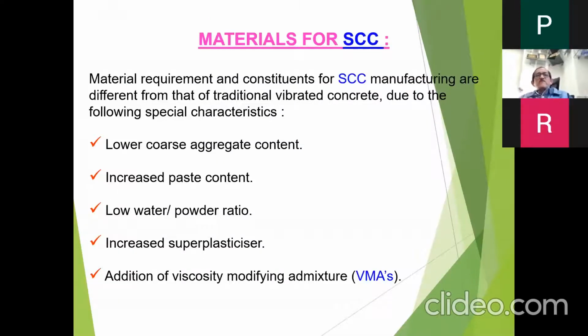Then materials for self-compacting concrete: lower coarse aggregate content, increased paste content, lower water powder ratio, increased superplasticizer, or I would say the use of hyperplasticizer, and addition of viscosity modifying agent. When I say hyperplasticizer, it would also mean a high range of superplasticizer. So there would be mid PCs, there would be high PCs, high range PCs, and addition of viscosity modifying agents.